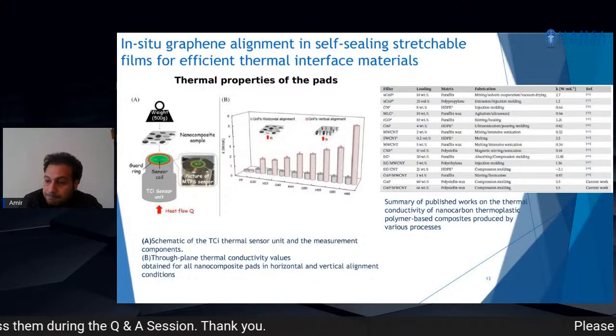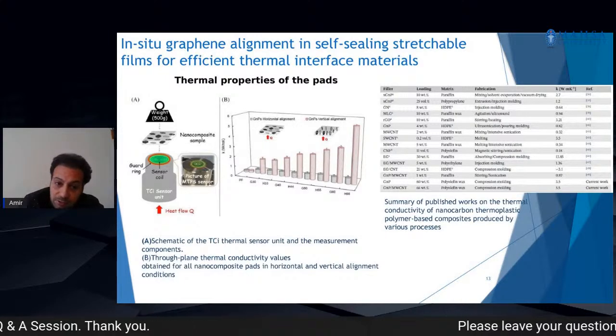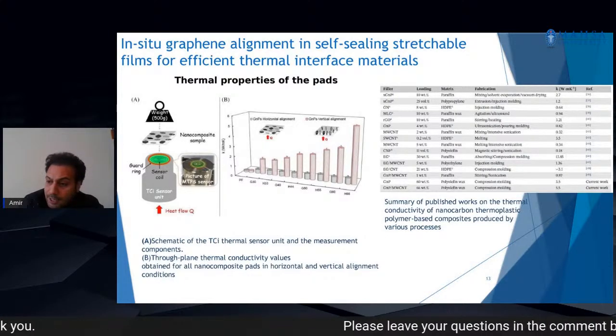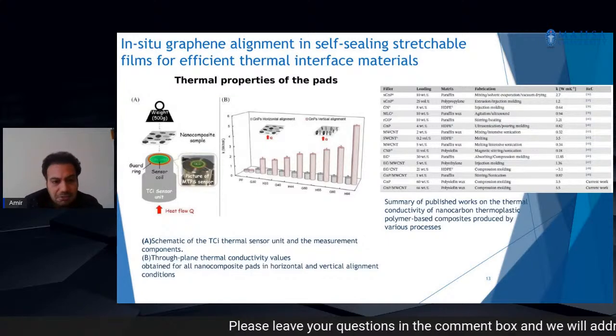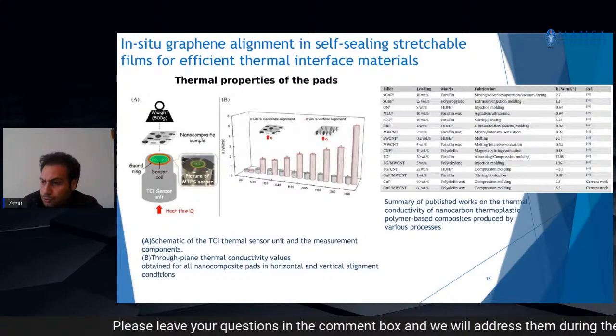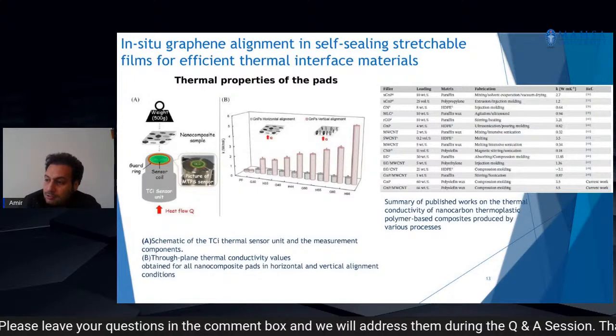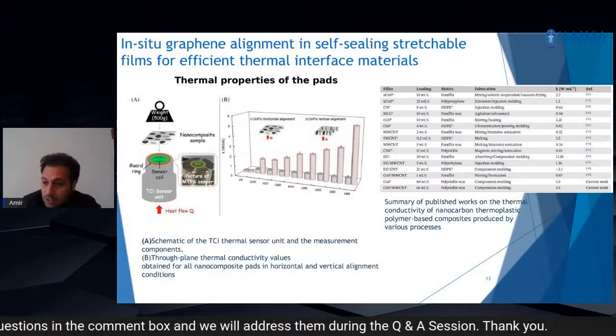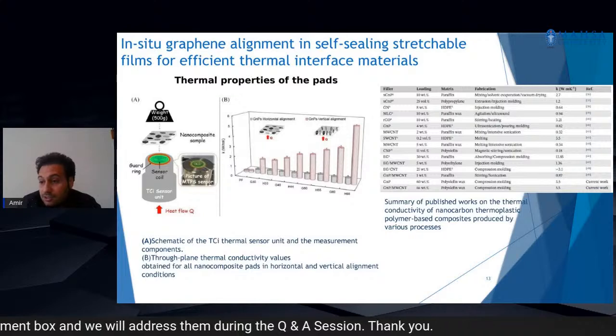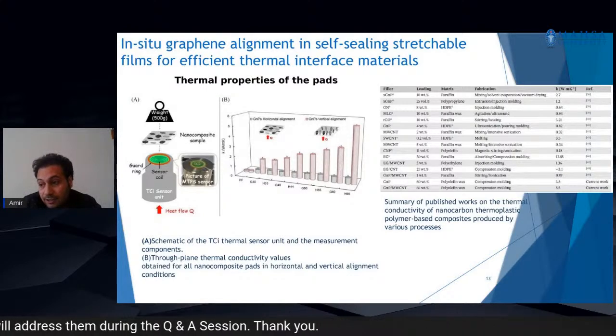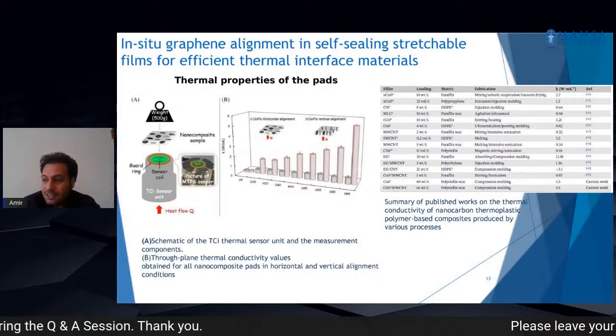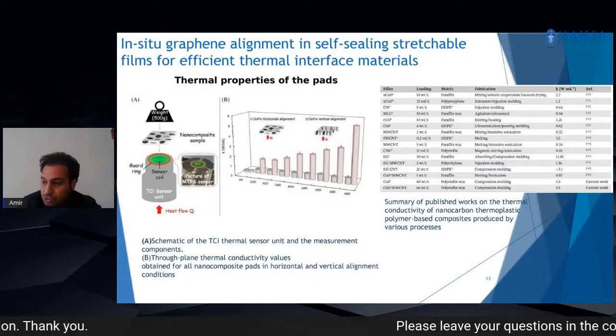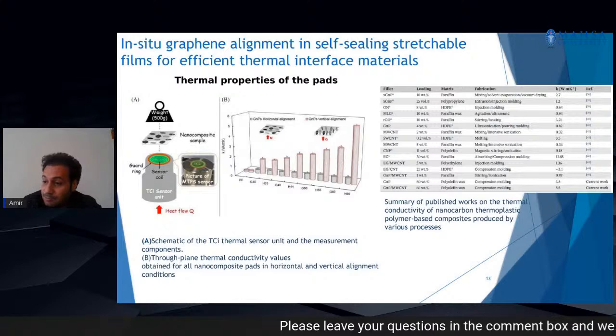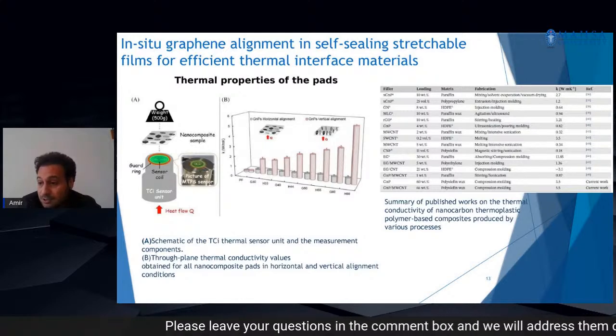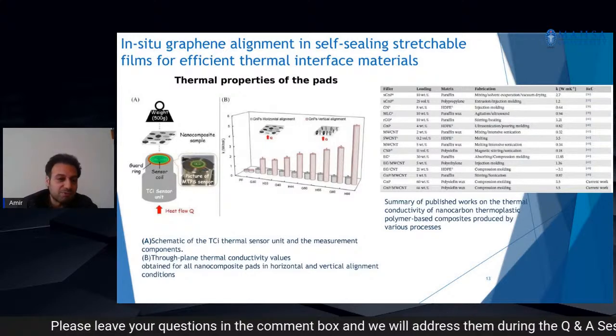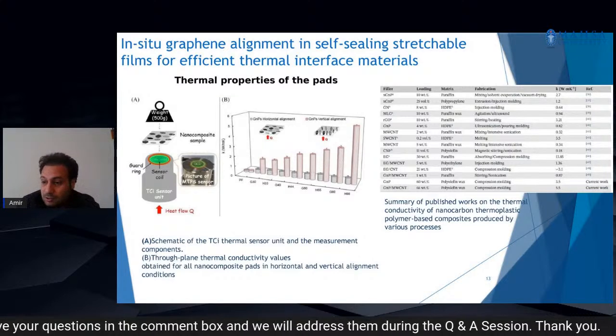Paraffin alone has very low thermal conductivity, around 0.2, which is independent of the hot press condition. Thermal conductivity of the horizontally aligned GNP pad is higher than the pure paraffin for sure, but even at the high GNP loading, 60%, the thermal conductivity increased by 5 times to around 1.